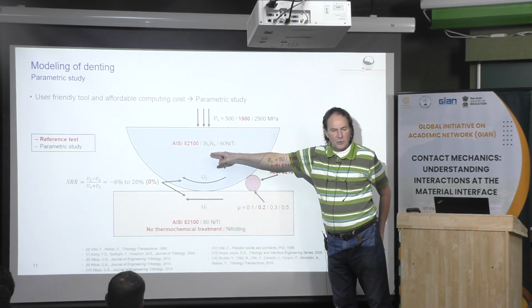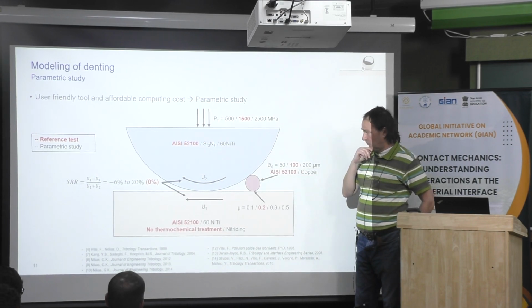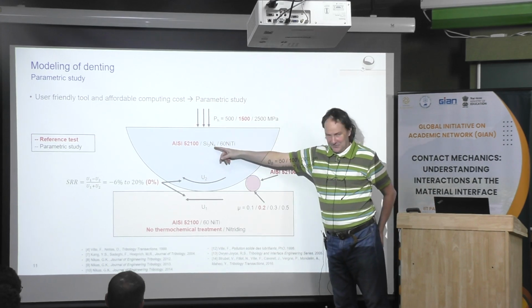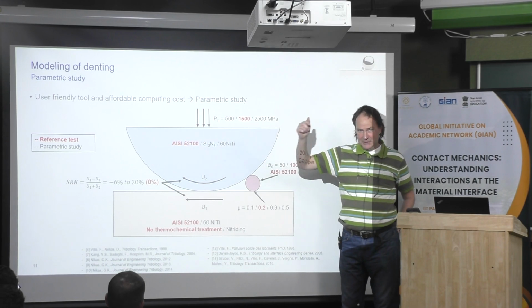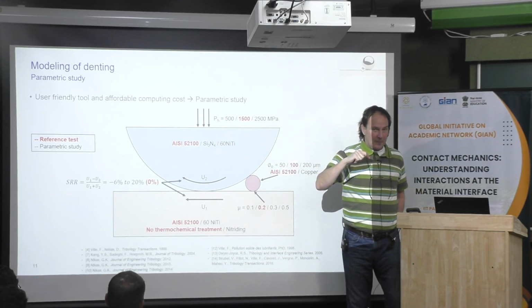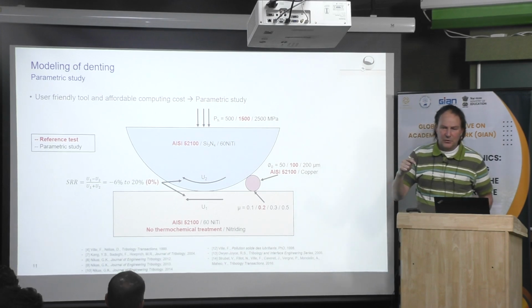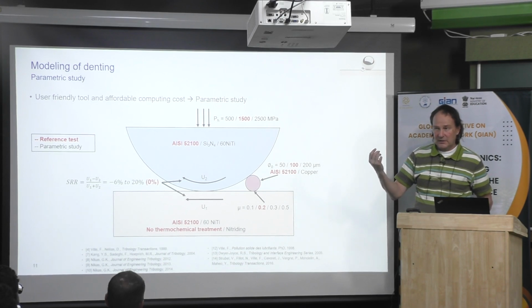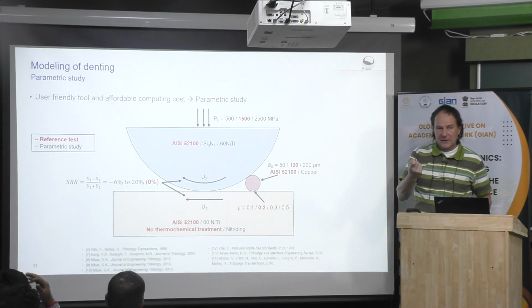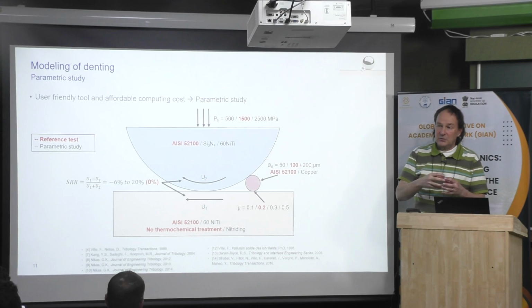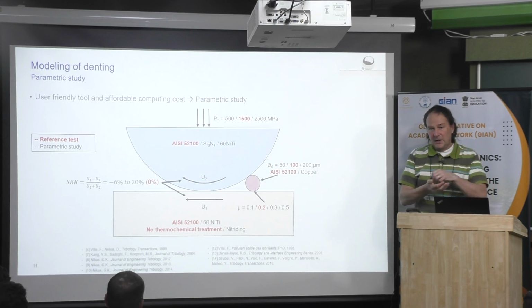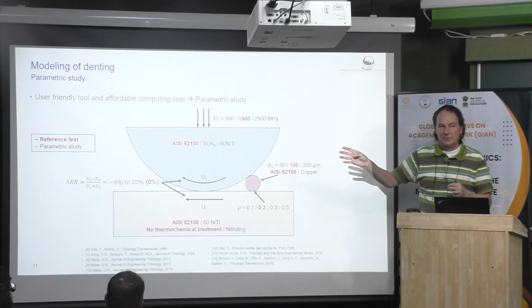Something interesting with that, we have been working with some Japanese guys in the past, not too far away. And in fact, with the same name, you can have very different materials, because it depends if it is coming from a buyer, for example, or from a Japanese producer. This is made of, of course, silicon nitride, but also with some cement, which is 3 to 5%, and which is mostly based on yttrium, and it is hot pressed at high temperature, but depending on the manufacturer, Toshiba, for example, and Bayer, do not use the same temperature and the same pressure. And then you have the same name, but this is not the same material at all.